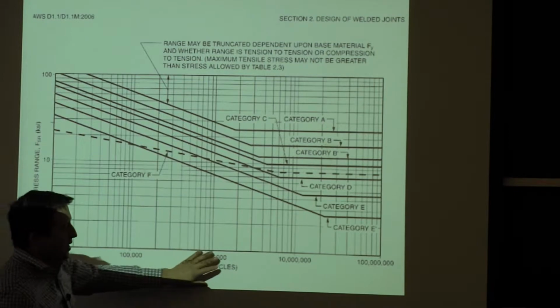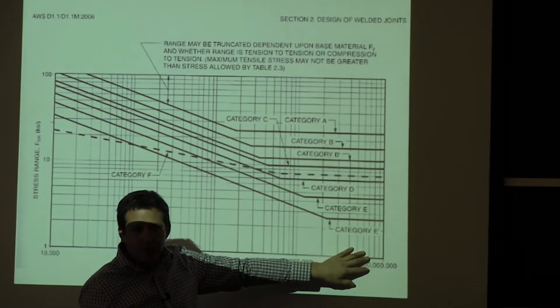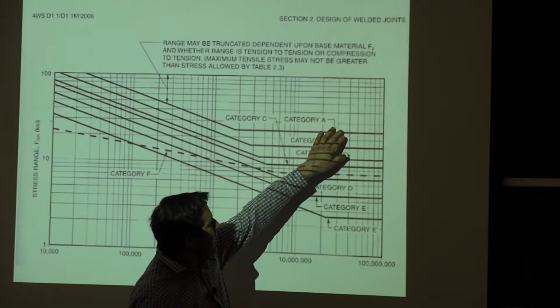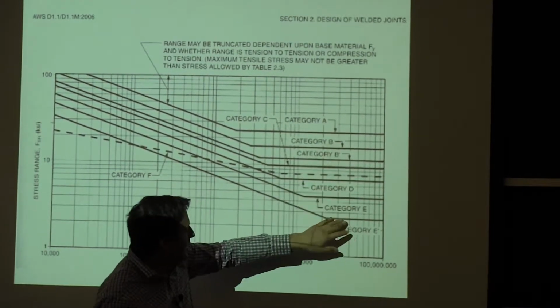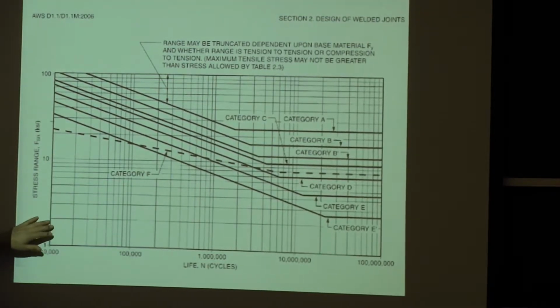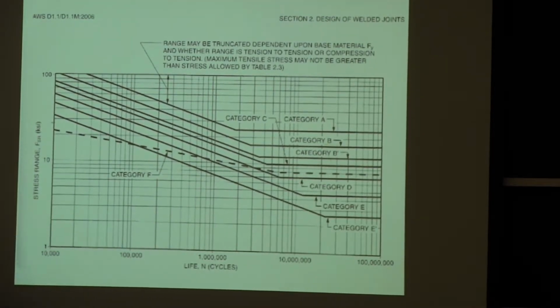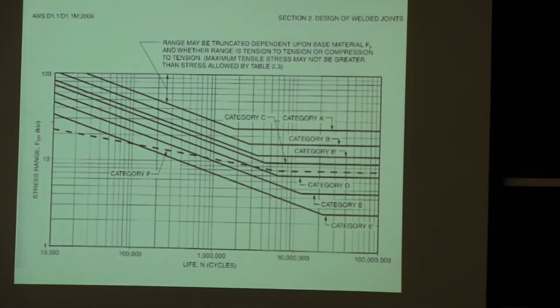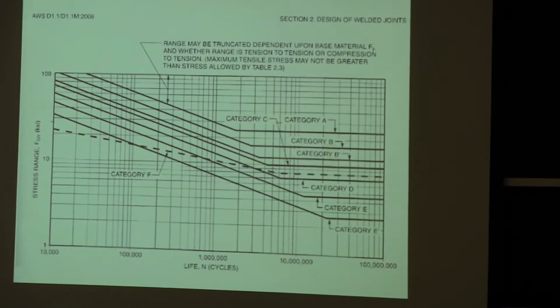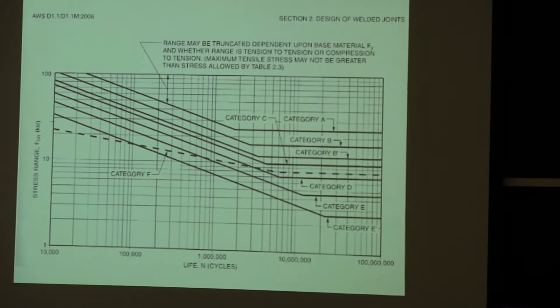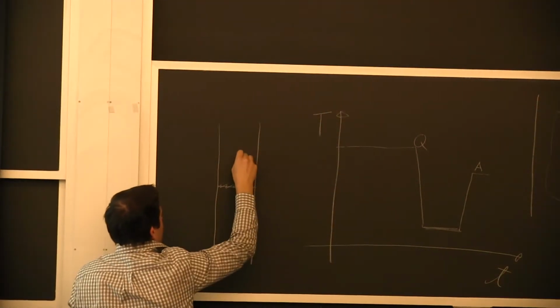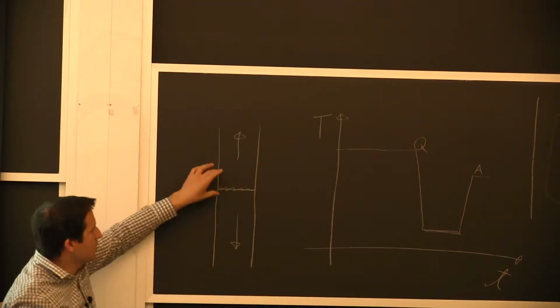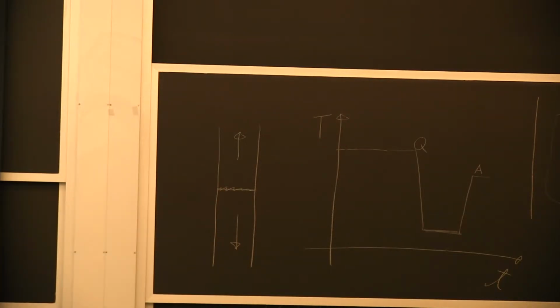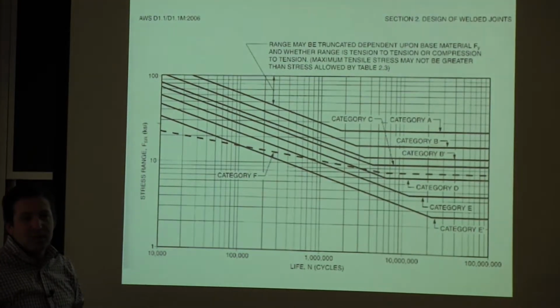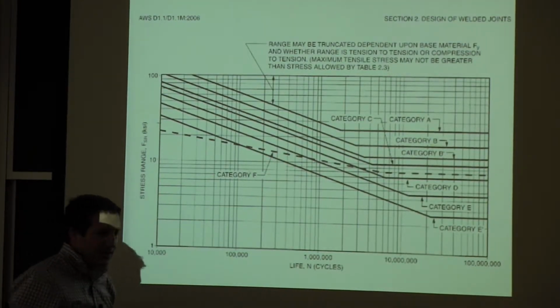So if we're looking at something that would be under vibration condition, or we don't know how many cycles we get, we'd be looking here at the base material being above 20 KSI, and then the allowable, if it's a joint that's loaded in a transverse direction, say I have this detail where this is my bar, I have a cut in it, and then I weld this way, and I'm loading in this direction, and then I have an attachment that's in the other direction. It's not a groove weld, it's a fillet weld. You're looking at a stress here that's less than 3 KSI. So it's a factor of more than 5 on what you're permitted.